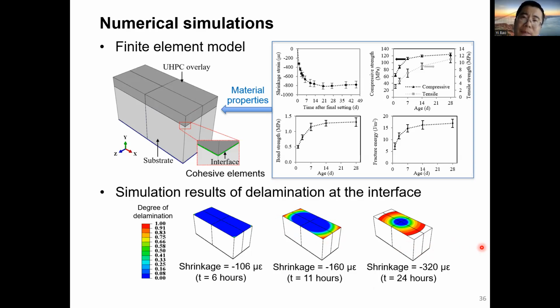So we could strategically deal with the trade-off between shrinkage and the mechanical properties. So eventually, my collaborator, Professor Wina Meng from Stevens, her group developed a version of ultra high performance concrete with lower shrinkage but higher bond strength. Eventually, they eliminated interfacial delamination.